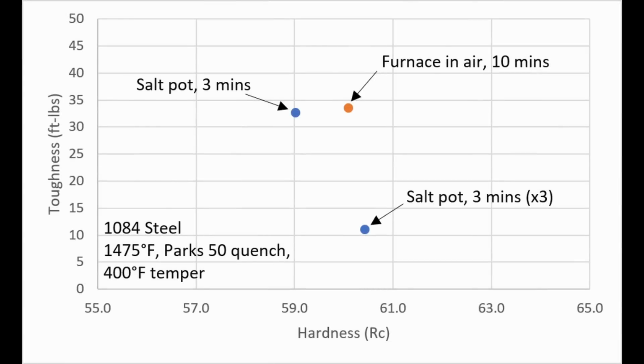So, in this case, the salt pot heat treatment for 3 minutes, I got a little bit lower hardness, about 1 Rockwell C lower hardness than the normal furnace temperature at about the same toughness. So no improvement in toughness and slightly lower hardness. Though nothing to get excited about, if there was an improvement in the grain size, it didn't show up in toughness. Maybe there was a little more carbide left in the steel with the short soak time, so maybe there can be some advantage to that, but no major improvement in properties in terms of the hardness-toughness balance. The normal furnace did better.